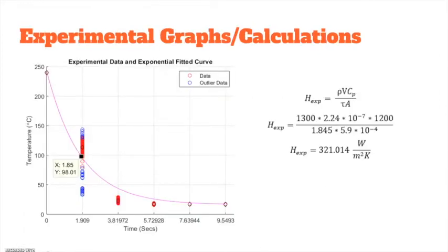The system started at the original nozzle temperature of 240 degrees Celsius, and it eventually reached steady state around the room temperature of 16 degrees Celsius. There were some outliers as seen in blue. These values were discarded to better plot the exponential fitted curve. We then found the tau of the system by calculating 63% of the change in temperature. Once the tau was found, the experimental convection coefficient was calculated.